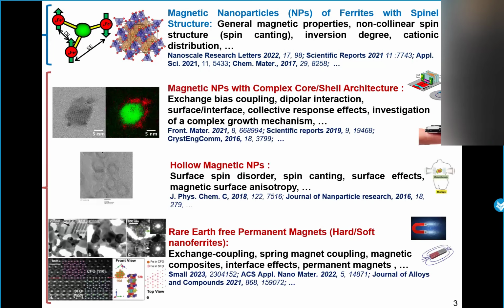Among these nanostructures, the spinel structure is a very rich system because of the correlation between the spin structure, cation distribution, and general physical properties. And by introducing a new magnetic phase like an antiferromagnetic phase, and by changing the morphology, we obtain more complex structures like core-shell, hollow, and nanocomposite. Jean-Marc previously presented the nanohybrid system, which is also very interesting for biomedical applications. This complex architecture allows different interfacial mechanisms like exchange bias, big spin disorder because of the surface effect, and exchange coupling at the interface between different ferrites.